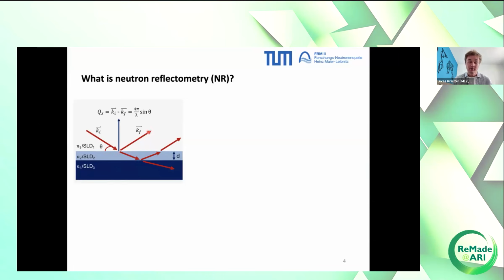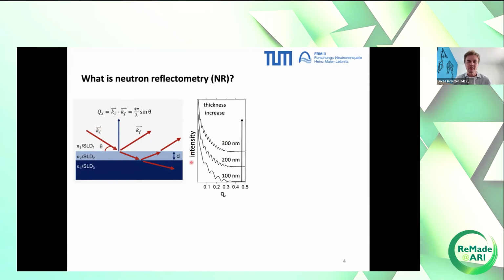Then you have an outgoing or scattered neutron. You have the 2 wave vectors, the incoming and the outgoing neutron. And the subtraction gives you the momentum transfer Q. And this Q is only in Z direction, so you get only information in vertical film direction. That's why we name it QZ. And the typical reflection curve would look like this. So you would have the intensity as a function of QZ, momentum transfer.